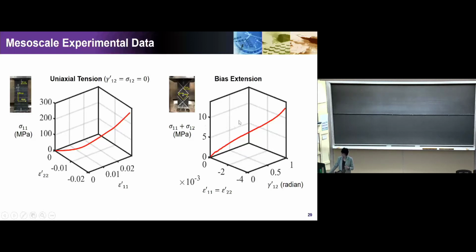We also collected some very limited data taking into account the shear behavior. That is the bias extension. You can see I marked the weft and the warp, two directions there. With that, we have some more data on how the behavior is different when the shear angle changes. We actually reserved this data for validation. We didn't use this data at all, even though the shear angle gamma 12 is an input of the model. We used it to validate how good the calibrated model is.